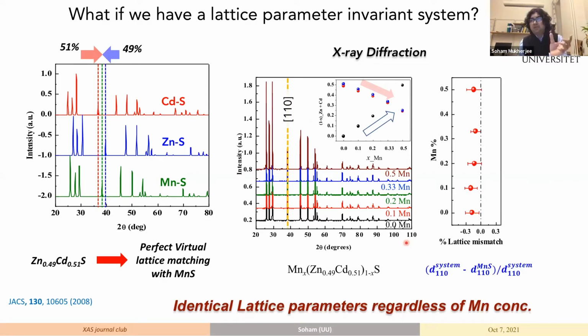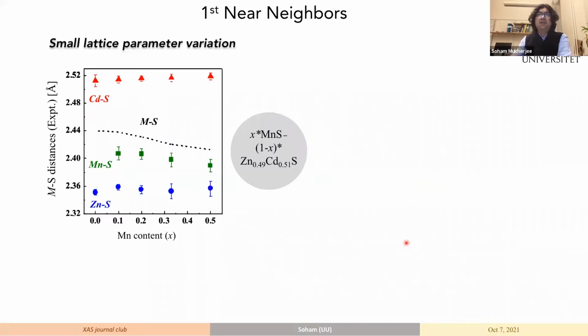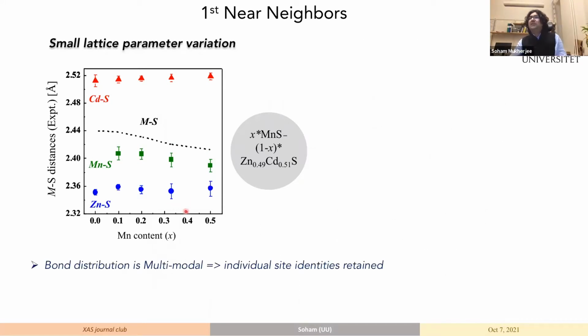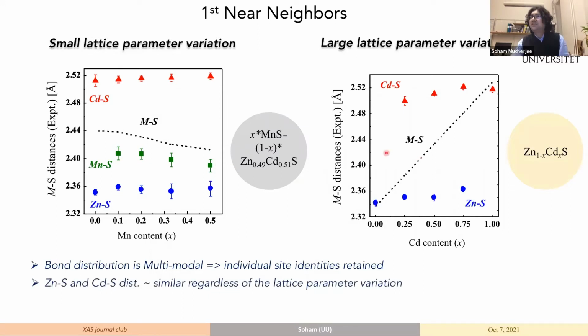So now we compare this with our previous results, and this is exactly what we get. There is hardly any variation of the average metal to ligand distance, but there is a clear trimodal distribution now. Now, when we compare this with the previous result, we see that not only that, the zinc sulfide and cadmium sulfide distances in a lattice parameter variant system and a lattice parameter invariant system are almost similar.